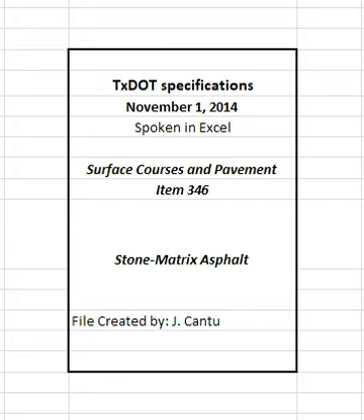4.9.2.4.5 Hamburg wheel test. The engineer may perform a Hamburg wheel test at any time during production, including when the boil test indicates a change in quality from the material submitted for JMF1. In addition to testing production samples, the engineer may obtain cores and perform Hamburg wheel tests on any areas of the roadway where rutting is observed. Suspend production until further Hamburg wheel tests meet the specified values when the production or core samples fail the Hamburg wheel test criteria in Table 8.